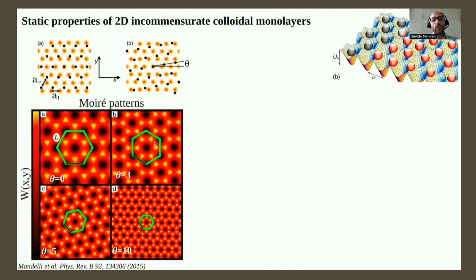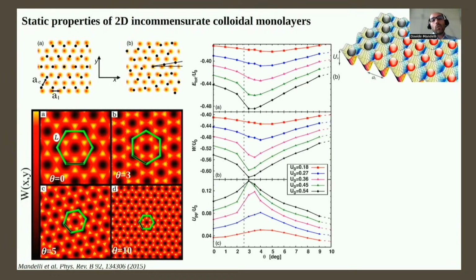There are analytical expressions that can be given for the geometrical properties of the Moiré, which I spare you, but it is possible to derive them quite straightforwardly. And now, if we look at the evolution of the total energy of the system as a function of theta, which is shown here, we see that different curves correspond to different values of the substrate corrugation amplitude. So what we see is that there exists a clear minimum at a finite angle.